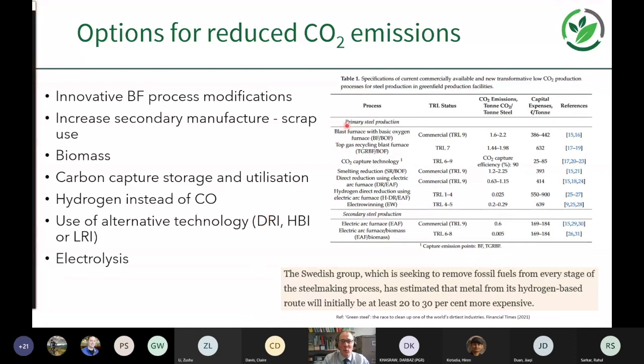So options for reduced CO2 emissions. In the table, we can see the blast furnace with the basic oxygen furnace route for producing steel produces between 1.6 and 2.2 tons of CO2 per ton of steel. And then top gas recycling brings that down, with carbon capture brings that down further. Then you've got direct reduced iron with the electric arc furnace, which starts to bring it down further. And then when we start to consider hydrogen, we're bringing those CO2 emissions, or specific CO2 emissions, right down.